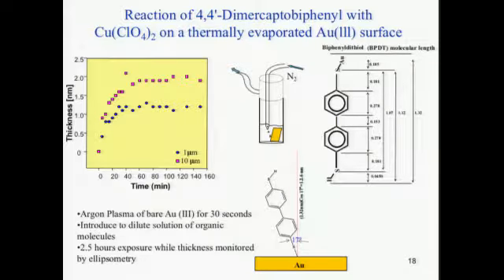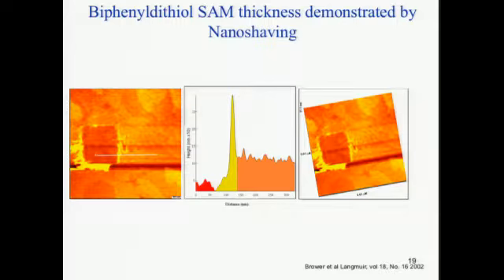That's why we do it in nitrogen, and we take a lot of care about how much time and what the concentration is, hoping to drive the gold-S bond as opposed to a disulfide bond on the surface. Most of the methods that I showed you for characterizing the material are what we call relative methods. It's relative to a previous refractive index, or to some other orientation on the surface. But the one thing about using scanning probe microscopy is that it's definite: it's either this height or it's not.